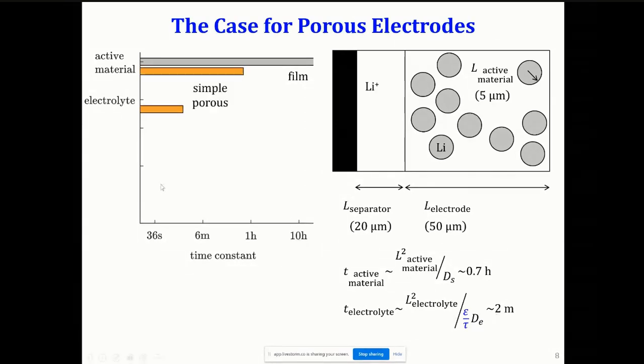So if you put it now on the time constant plot on the left, that is how things would look like. When we go for a porous electrode, we are making a conscious choice that since the most sluggish part was the lithium diffusion in solid phase, we are trying to decrease that time constant. Now, the penalty we get for that is that we are now increasing the time constant for lithium ions to pass through electrolyte.